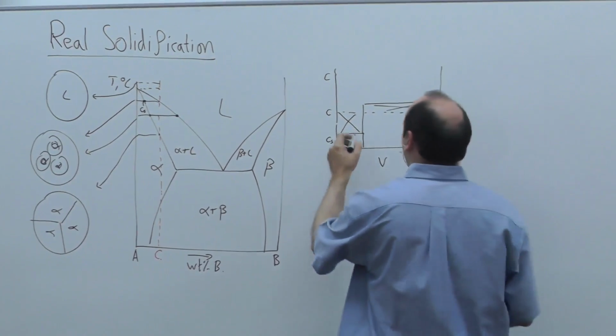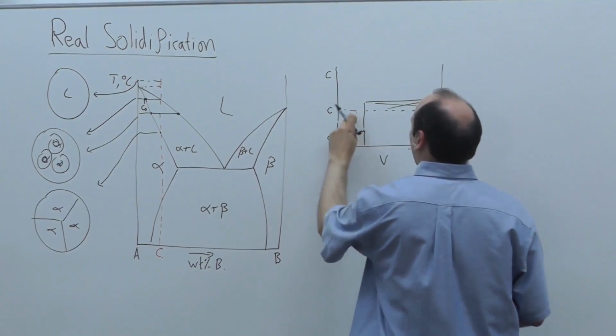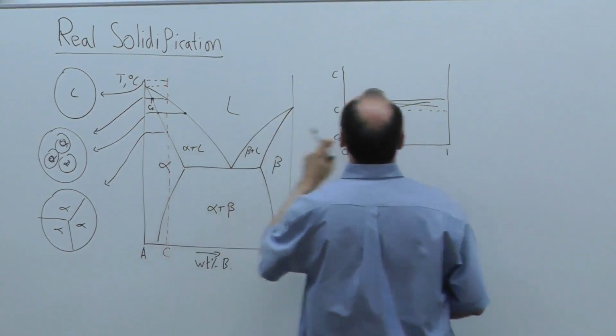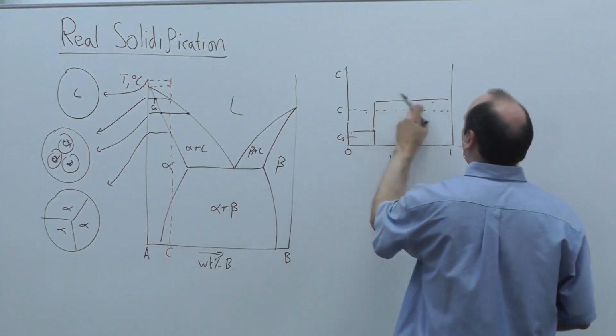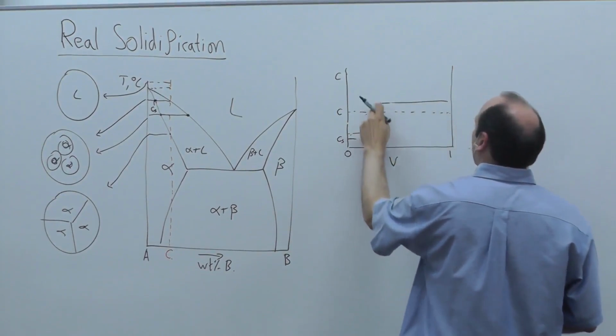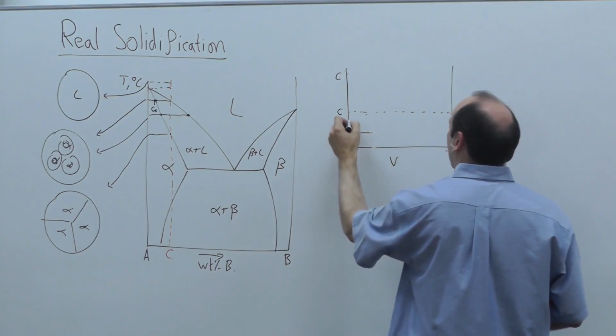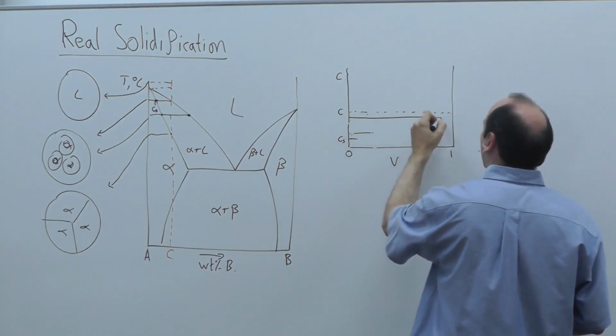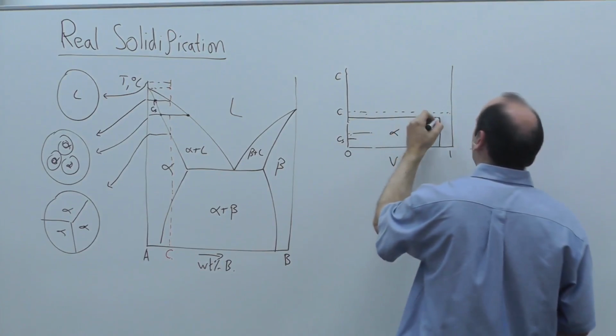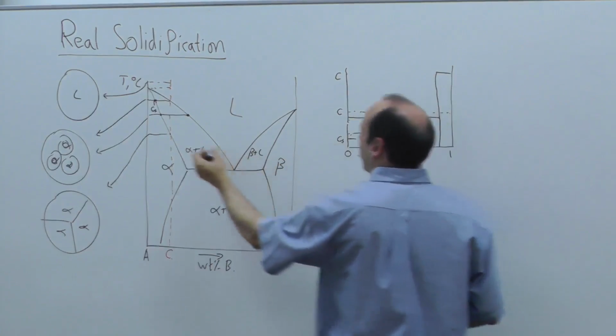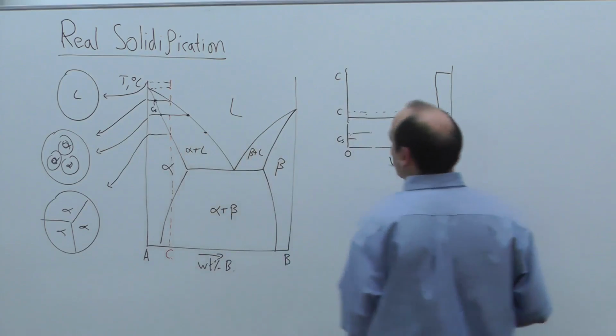Until we get further on in solidification, when we go further on and down to a temperature near to the point at which we're pure solid, then we'd be in a situation a bit like this. The composition of the solid would have increased again, and we'd be something like that. That'd be all our solid alpha phase. And then we'd have some liquid that would be very, very enriched, over at this composition here.